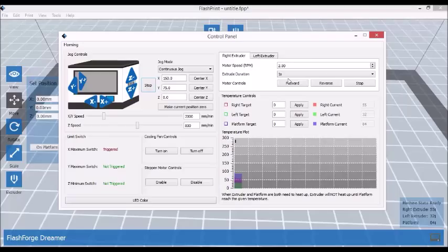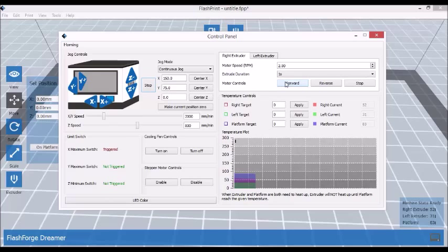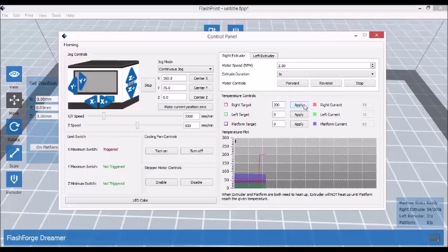When you replace your filament that you used before with rubber, you will have to feed it slowly and extrude from the software just to make sure that it cleans out and it doesn't jam. For loading purposes, I'm using 200 degrees on the nozzle. And for printing purposes, probably 175 to 200 degrees is suitable. It depends on the printer.